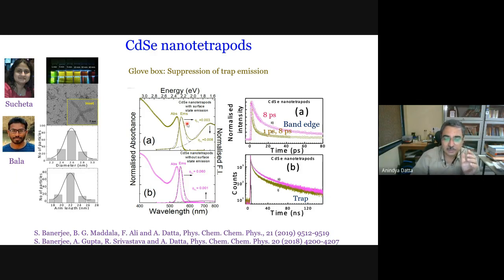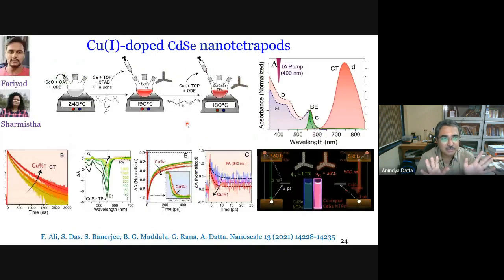We thought, is it possible to dope the nanoparticle, knowingly add some ion or something, which would lead to separation of the electron and hole wave function, and does that give strong photoluminescence? This was already reported in spherical nanocrystals. The challenge was doing it in nanotetrapods. So with a little bit of effort, Sucheta and then Fariyad was successful in making copper doped nanotetrapods.